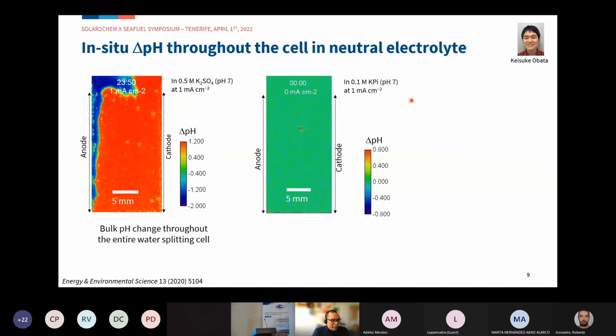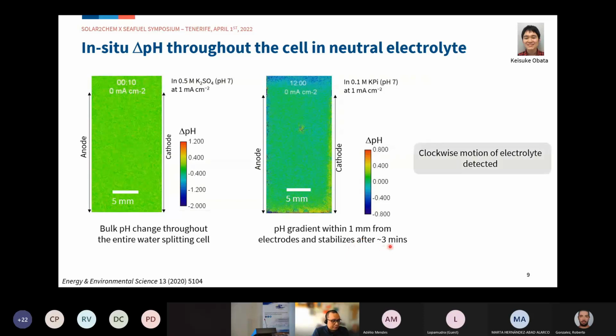Now if we compare that with the case where a buffer is introduced, a phosphate buffer, we can see the pH gradient still appears but is minimized. It's constrained to within 1 millimeter of the electrodes, and it stabilizes after about 3 minutes.